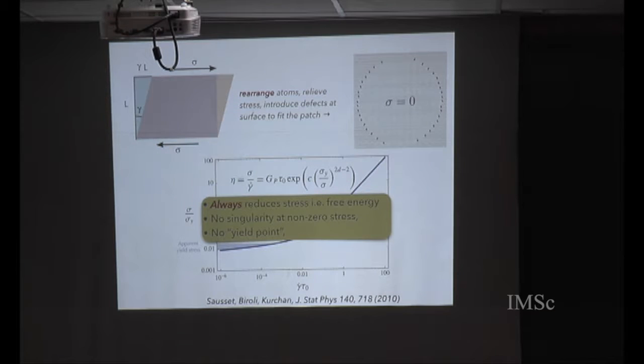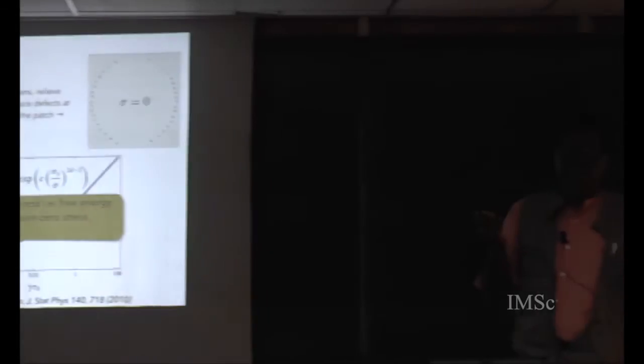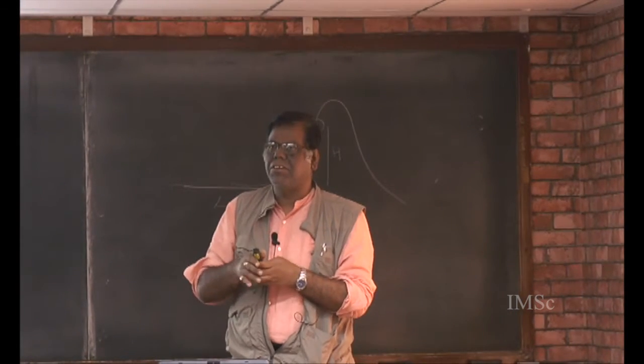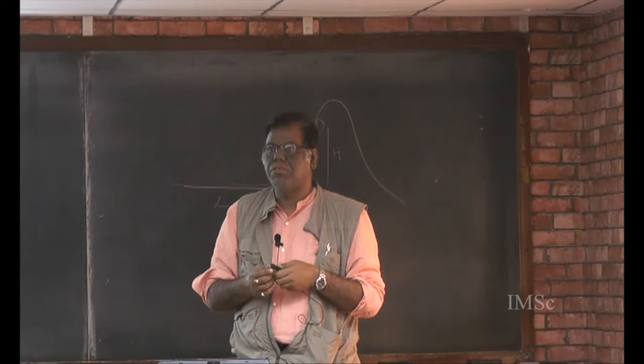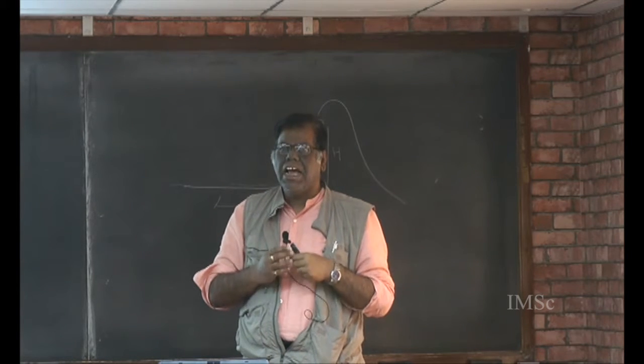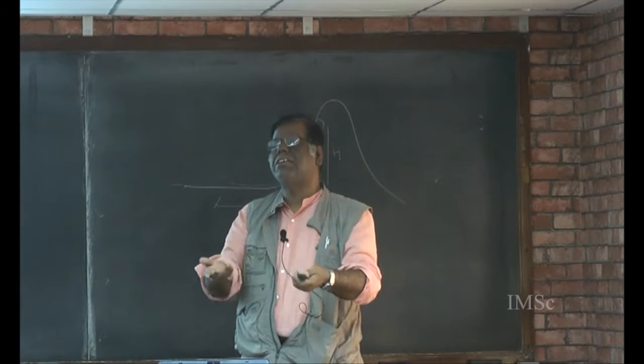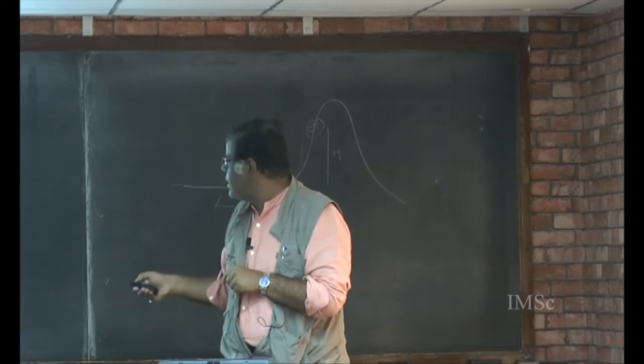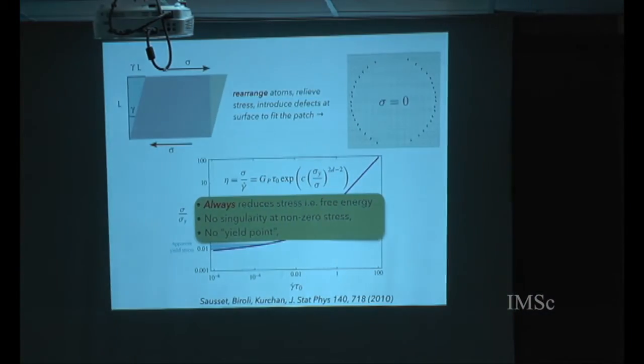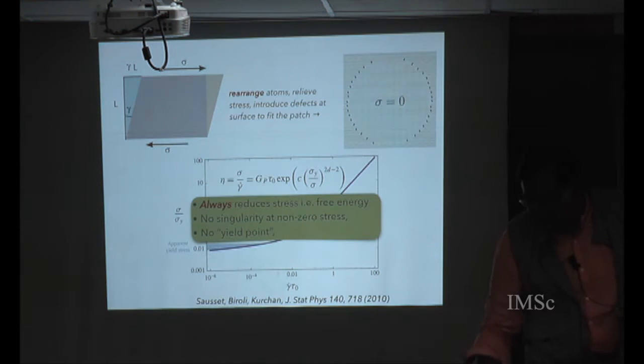It shows that you can always reduce the free energy of a stressed crystal. You can always reduce the bulk free energy. You have to pay only a surface free energy cost in putting in dislocations. There is no singularity, so this whole business of yield point is just fake. There is a knee in the curve, and if you stress something, it flows. Even a crystalline solid flows, but it flows at an extremely tiny rate which you can't measure. As the stress increases, this flow rate becomes measurable, and that is what you call the yield point. I would like to emphasize this particular point, that it always reduces the free energy, and I would like to invite you to think about this already as the talk progresses.